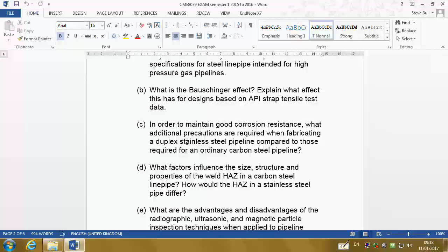You have to control the composition of the weld. You have to make sure that the austenite to ferrite 50-50 ratio is maintained. So there are precautions about the heat input, and there are precautions about the composition of the welding consumables. They generally have higher nickel content than the alloys that you're welding. But the whole point about it is you maintain the 50-50 austenite ferrite corrosion resistant composition. In this case, I think this is more a question that will be a text question with lots of description rather than a diagram. There isn't something obvious for that.